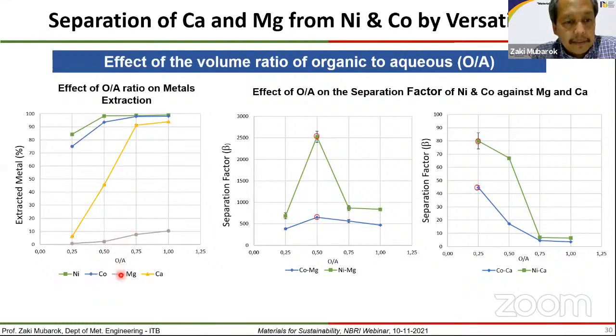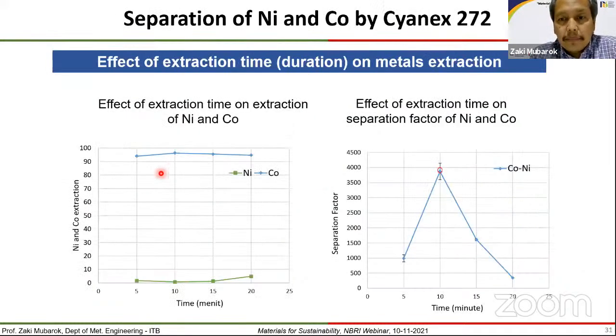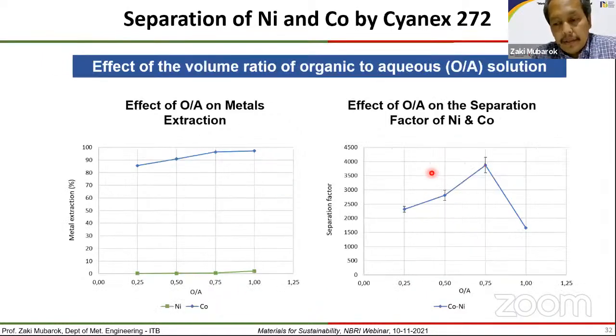Here the magnesium, calcium, and separation of nickel and cobalt is not a problem. Basically we extract cobalt here in organic phase, nickel in aqueous phase, and these are the separation factors. Also the effect of organic to aqueous ratio, so no problem, we can separate.